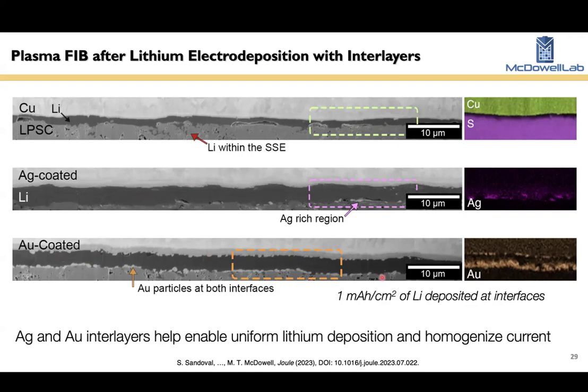The gold-coated one is quite interesting, though. What happens is the lithium deposits, it alloys with the gold to form a lithium gold alloy, and actually this gold film then breaks up into particles, and you can see these lithium gold alloy particles at both interfaces after lithium deposition. So there's a very dynamic interlayer, a very dynamic interface, actually. Lithium reacts with gold, the gold particles break up, and part of that gold is then carried across the interface as lithium grows. So when you strip, the gold comes back and lithium is removed from it, and presumably it comes back to the interface and sits there as well.